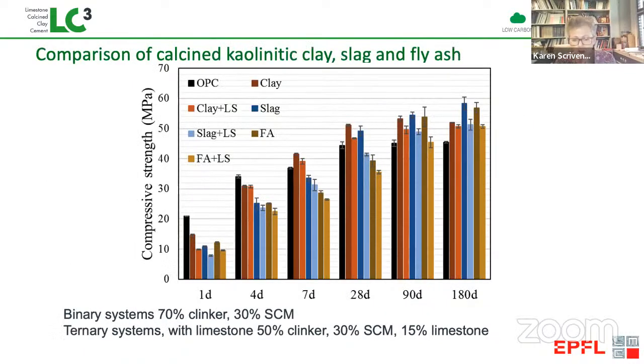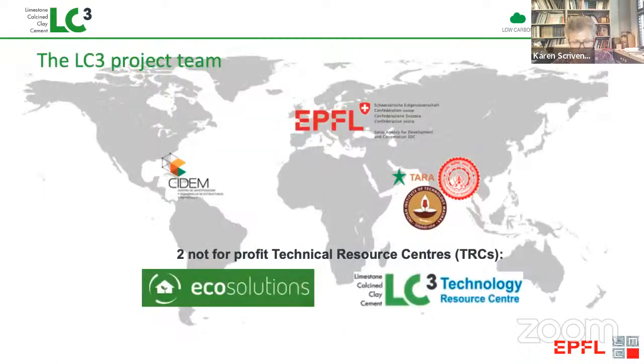In this slide, we're comparing calcined clay with fly ash and with slag alone as pozzolans and also in combination with limestone. And the key message you can see is that in the long term, all these mixtures come to very similar strength, but the mixtures with calcined clay, which are in the red, are achieving that strength much, much more quickly than either the slag or the fly ash.